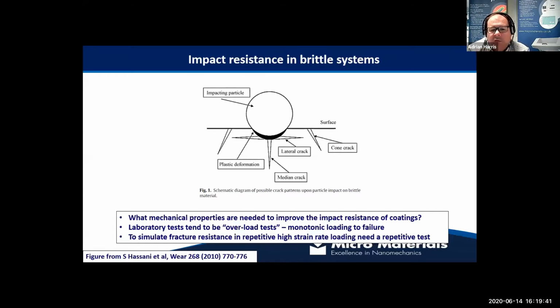So what's very desirable is to be able to take coatings at an earlier stage of development, deposited in small quantities on a test piece, and then perform some kind of lab scale test where multiple samples can be tested automatically with no user intervention, and give us a pretty good indication of what coatings we may want to develop further and put forward into a true cutting trial. It's important to note we're not trying to completely eliminate the concept of doing a true cutting trial. What we're trying to do is pre-filter materials which we want to put to that more expensive and time-consuming application test.